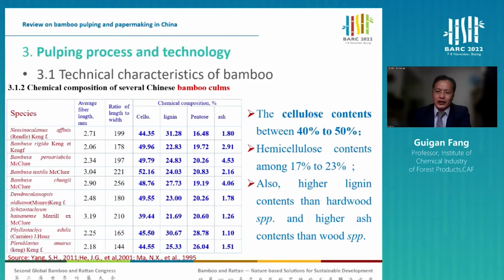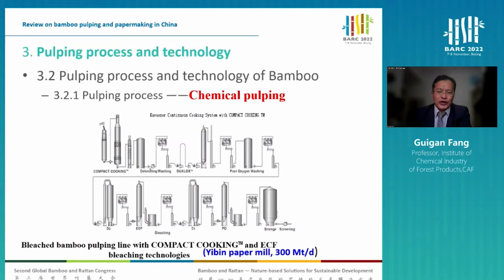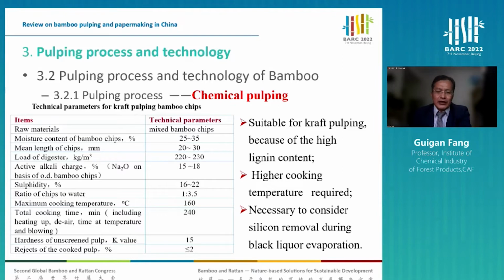Its cellulose content is between 40 to 50%, and the hemicellulose content is between 17 to 23%, compared with timber. The ash and pentose content are relatively higher, and the pulping process and technology makes it suitable for chemical pulping. In the 1990s, we introduced the COMPACT COOKING system with the production of 300 tons per day. That is to say 100,000 tons per year.